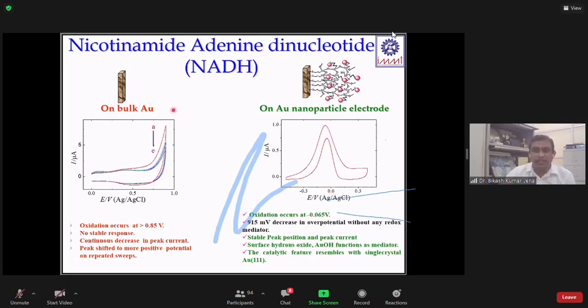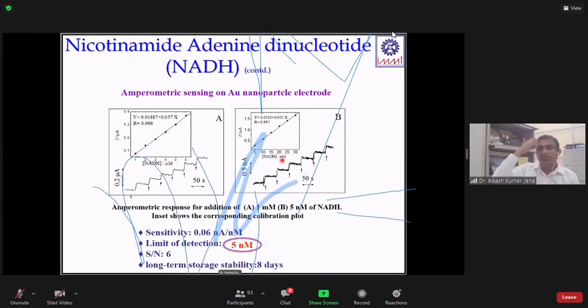And you can see the overpotential is reduced by about 915 millivolts. And the response is very stable when you put the nanoparticle. That's why we thought that this nanoparticle-modified electrode is good and sensitive for NADH. Let us use this nanoparticle-modified electrode to integrate the dehydrogenase enzyme onto the electrode surface.